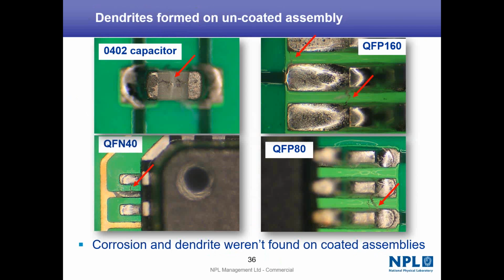These are the actual failures on boards that were not coated, but what we certainly saw was that the boards which were coated, either single coating or double dip, had no evidence of dendrite failure. Resistance would change because absorption of moisture will always occur, but we didn't actually see any dendrite failures. So it's all a matter of magnitude, what the condition was prior to and during the test. So these are all samples we see.